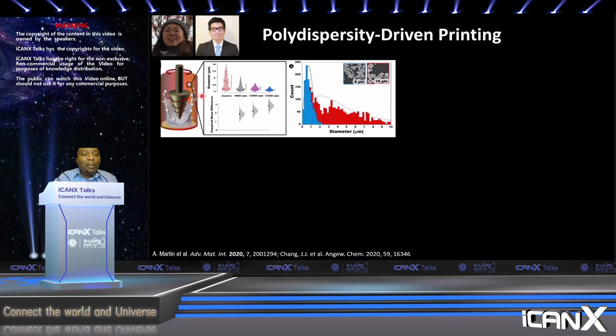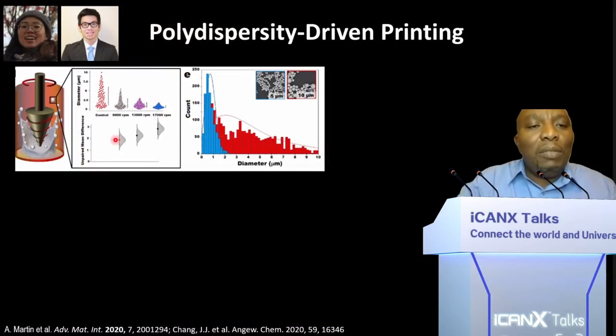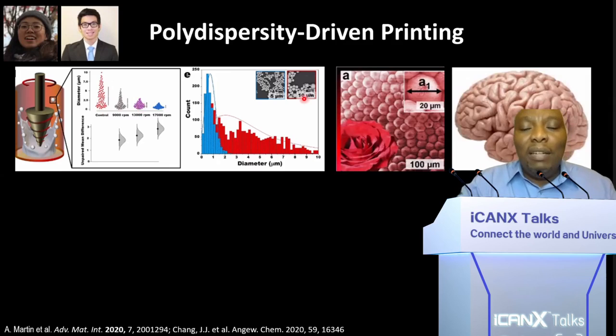But the other benefit we have with our method, the slicing method, is that we can tune the polydispersity of the particles. If we do this, then it allows us to dictate which proportion of the particles will go where on a textured surface. For example, if I have a very polydispersed sample and a very rough surface with multi-scale roughness, all the small particles can find their way to the tiniest crevices of the surface, and the largest particles will stay on top. Since we are working with capillary pressure, we can start tuning the particles we are producing for a surface like the rose flower so that it packs every crevice on the rose petal, or even a tissue like a brain that is very rough and has a very wide range of textures.